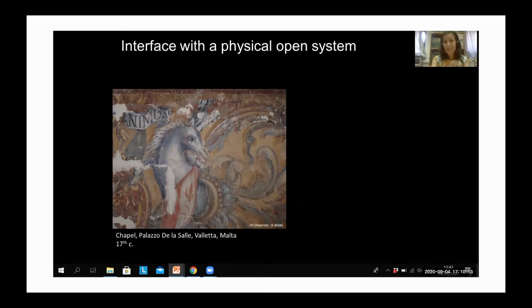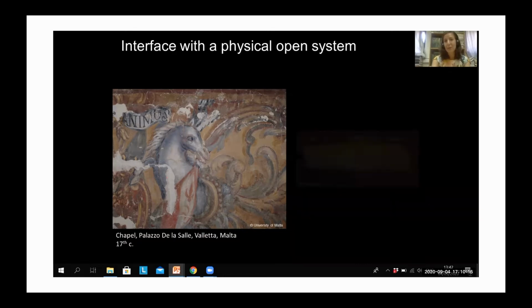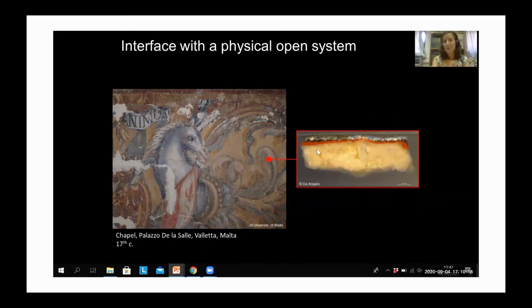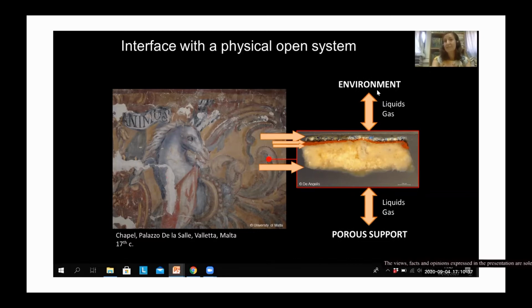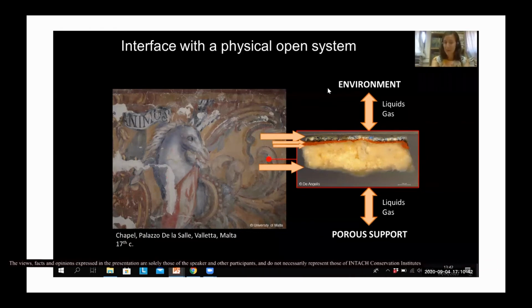if we take a tiny piece of a wall painting, a tiny sample, and we make a cross section of it, we can see its stratigraphy in detail. We can see that there are multiple layers, as I said, and multiple interfaces. And we need to think that all these materials throughout the stratigraphy are interconnected, connected at the interface with the environment on one side, so on the external part, and connected, of course, also to the porous support they lay on.